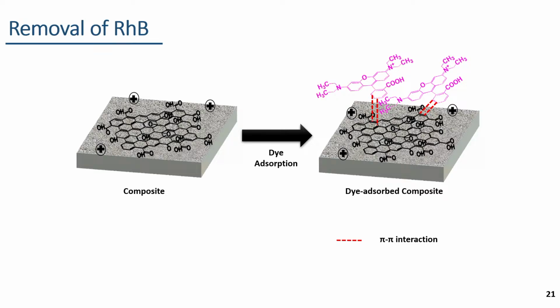Here, the rhodamine B adsorption onto this GO-based composite happens via two different pathways. The first one is the presence of the porous structure of the composite. These pores can trap the dye molecules during the adsorption process. The second is that the rhodamine B dye molecules can adsorb onto the partially reduced graphene oxide through pi bond interactions.